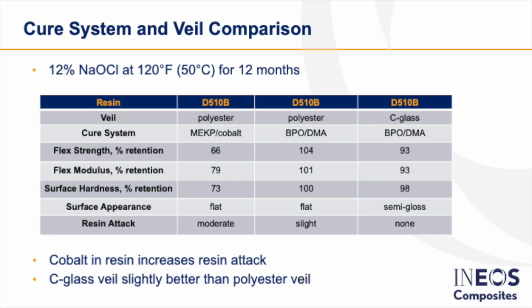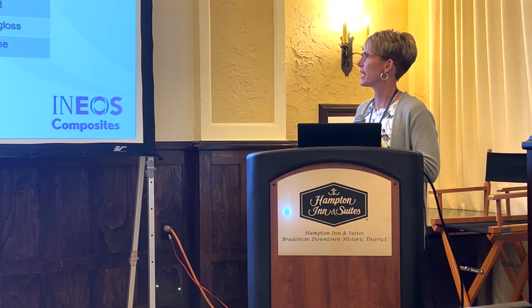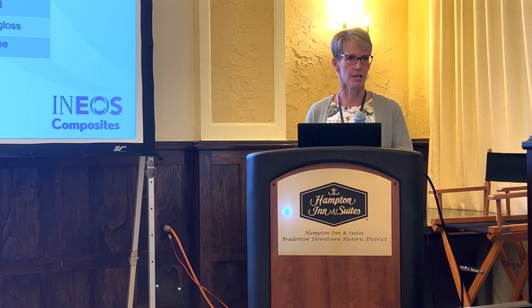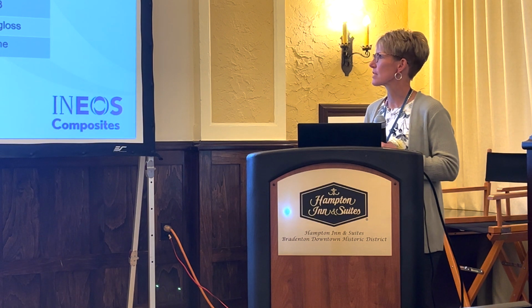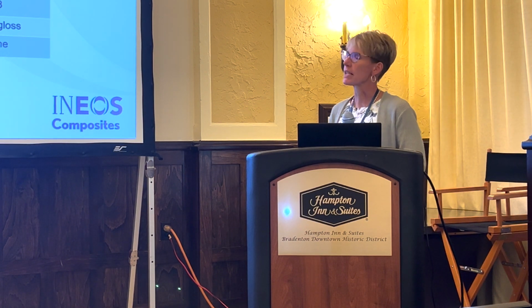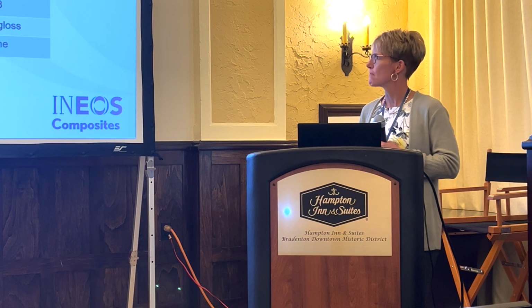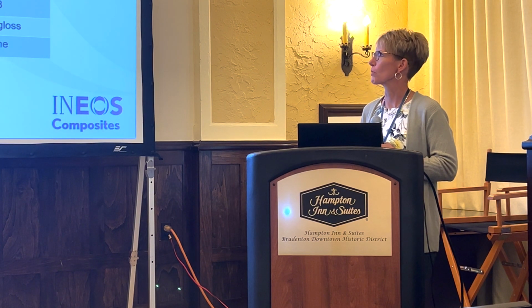Looking at the cure system and a veil comparison, again using the brominated vinyl ester resin, the C-glass veil provided slightly better results than the polyester veil. Very comparable retentions, but a little bit better surface appearance and no resin attack. So overall, again, your brominated vinyl ester resin with a BPO-DMA cure system and the C-glass veil provides your best resistance and best performance in sodium hypochlorite.